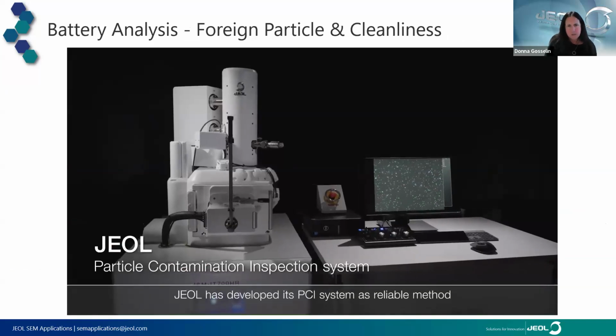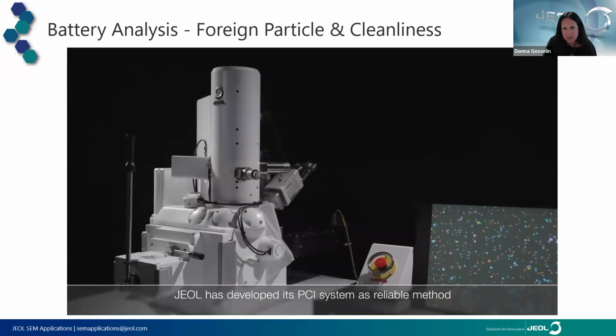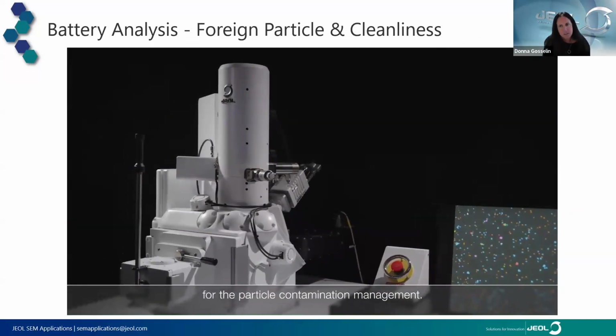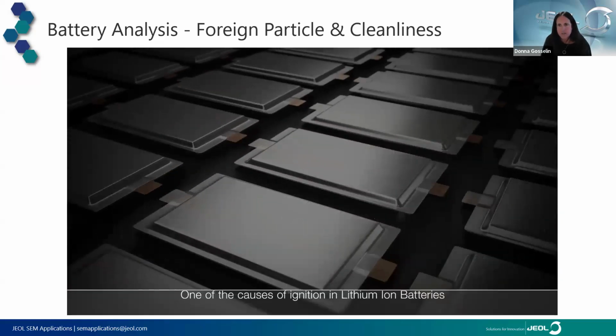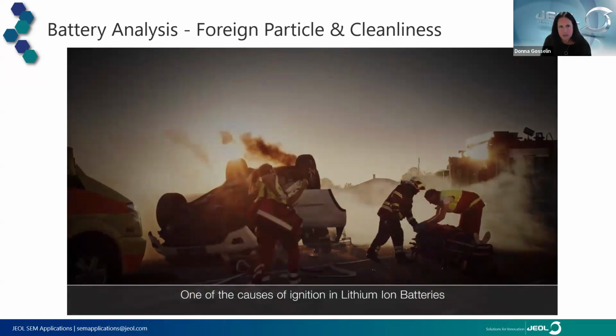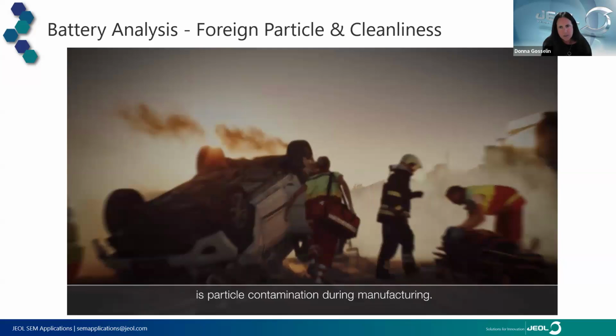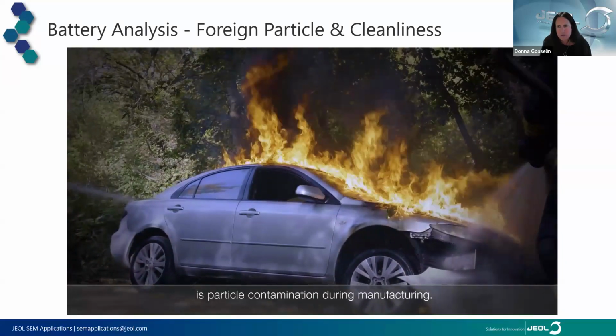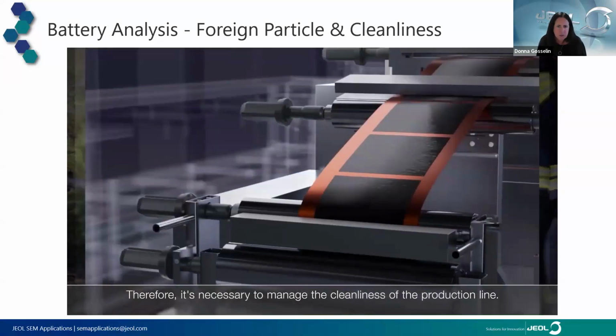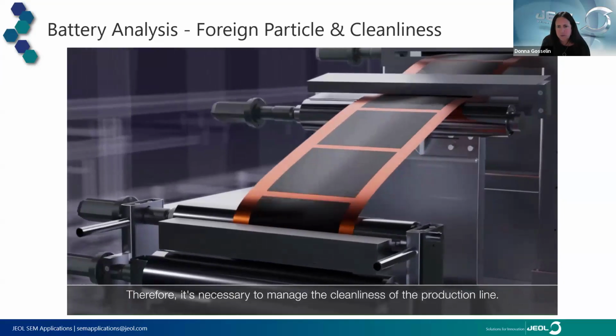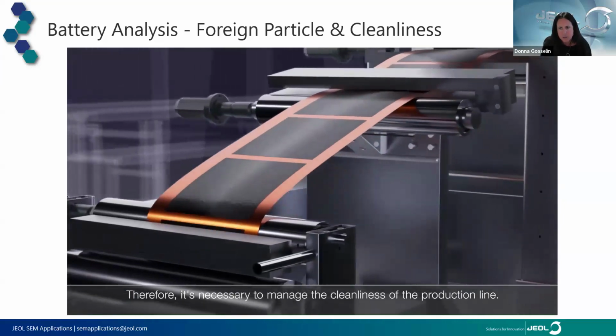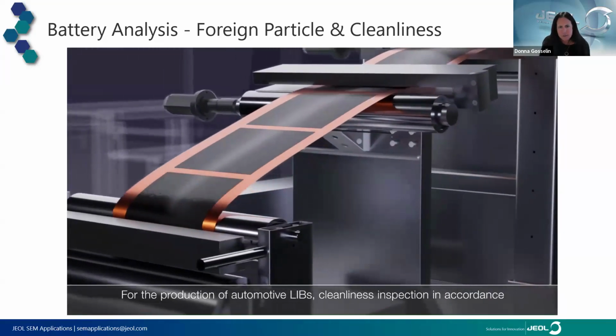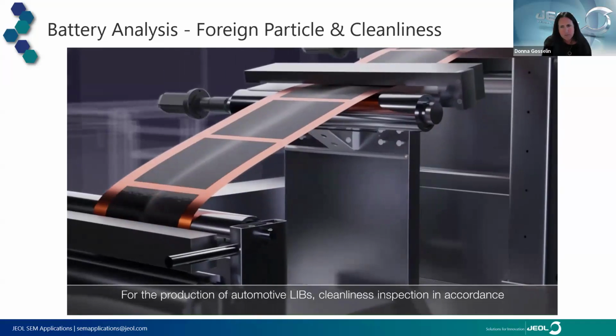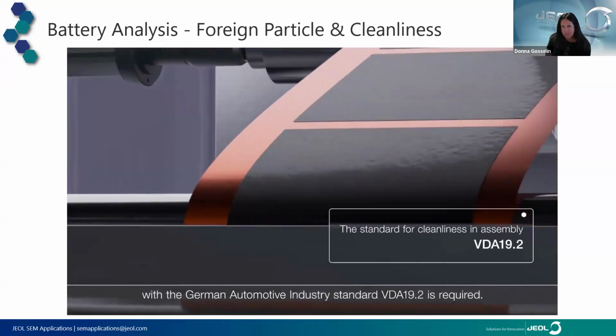If we want to take it one step further beyond particle size and shape, we can fully automate this process and not only get the shape, but classify the particles by composition. So one failure mechanism in battery systems would be thermal runaway reactions due to a short, maybe induced by foreign particles or defect in the separator. It's an extreme example and it doesn't happen very often, but it's important to avoid situations like that, right?